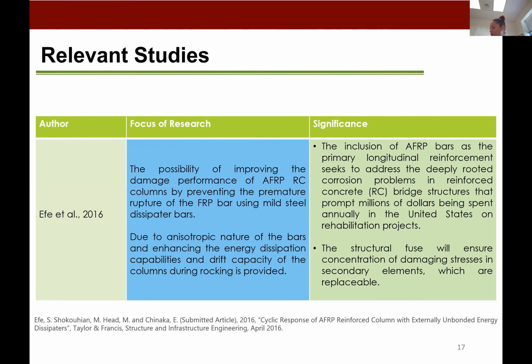So ACI 440 notes that the AFRP bars or FRP bars are not to serve as compression members. With that in mind, we are limiting the FRP bars as compression members, but allowing them to behave in a manner and in the range for which they do well as elastic elements, and to be able to respond elastically and ensure stress transfer to sacrificial members, which is where we decided to have these mild steel dissipators on the outside of the column system, where the steel dissipators would essentially allow the system to rock as well as dissipate energy, where we're focusing the damage in these secondary elements which are replaceable.